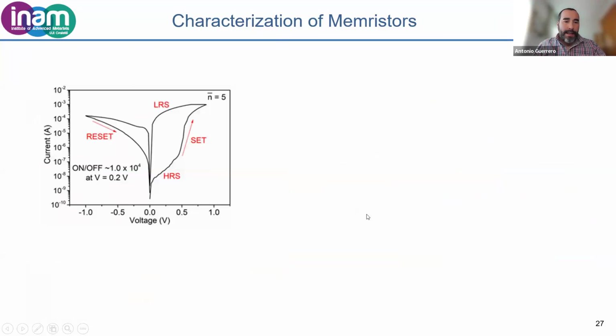So how do we characterize this type of materials if we are to use memristors from perovskite? So what we want is a device that in the IV curve that I explained for the solar cell, we want to maximize the hysteresis. So if we sweep voltage, we will be initially in the highly resistive state. This highly resistive state gives very low currents. And at some point, because we are applying this voltage and the ions are moving, the ions will reach the contacts, and the device will be able to extract lots of charge. And then the current will increase very fast. As you see here, this is a semi-log scale, so this y-axis is in the log scale.